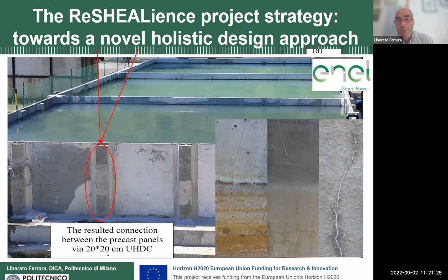2 years of exposure to cycles of emptying and filling the basin with this water, which is rich in sulfates. You can see that some erosion and some leaching has started occurring, whereas you have no sign of leaching in the central part of the picture. This is our UHPC material. And you can also see some evidence of crack sealing, of crack healing, on a real structural application. This is not lab scale, but a real structure on site. This basin is about 8 meters wide and 25 meters long, and the thickness of the walls is about 1.5 meters.